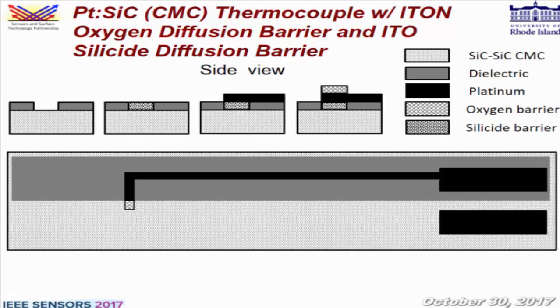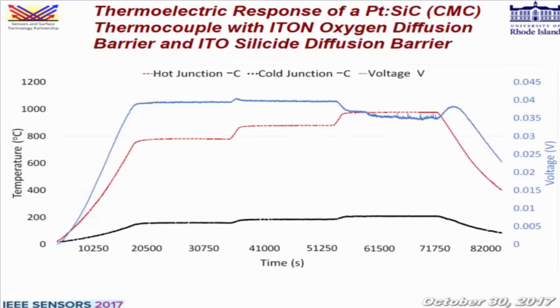So we went ahead and tested this. This test starts at 800, which is already a 100-degree improvement over the previous thermocouple. Then we go to 900, it works again. And then as soon as we try to go to 1000, the sensor fails. And 1000 is actually our target temperature. It's a typical temperature within the hot section of a jet engine. So this is as far as we've gotten with thermocouples. We need to make a 100-degree improvement, but we're almost there. We'll be there within a month or two.